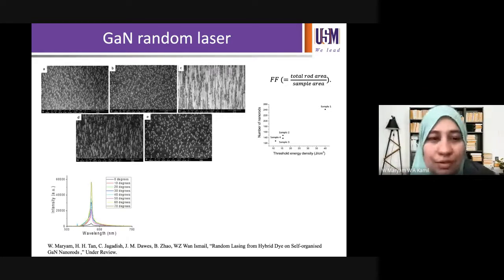And we also notice that the emission is everywhere. So this is the amount of angle that we change for our detector. So that's again showing that it's random lasing. If it was conventional lasing, Fabry-Perot, for example, then it would just emit in one direction. It wouldn't emit in multiple directions. So this is another proof of lasing. The reason why you see it going down is not because of the angle, but it's because we're using dye. So dyes degrade. Again, as I mentioned, there is a problem of degradation of the dye.